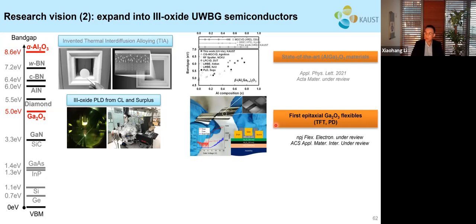The growth of epitaxial gallium oxide on flexible substrate is not trivial because most flexible substrates have a lower melting point, or they can be easily oxidized. In the meantime, ultra wide bandgap semiconductors, such as gallium oxide, prefer a higher temperature for crystallization. But in this study, we have demonstrated the first epitaxial gallium oxide TFT and photodetectors.